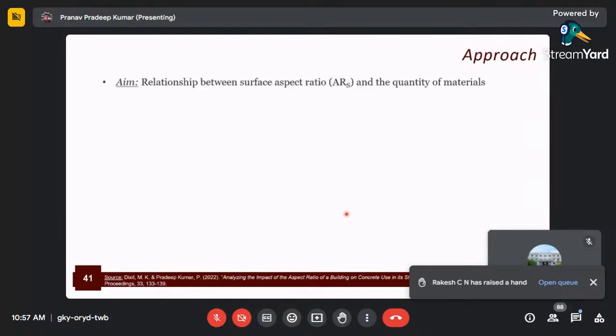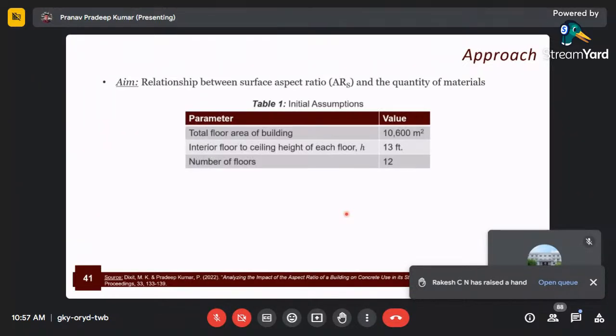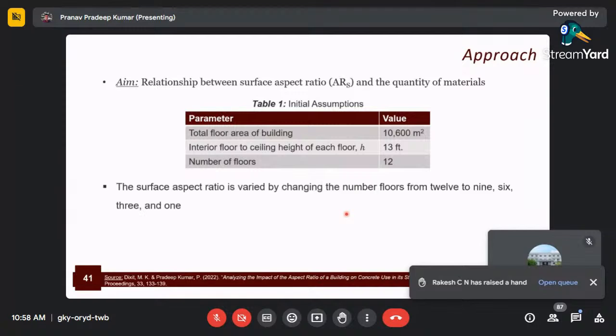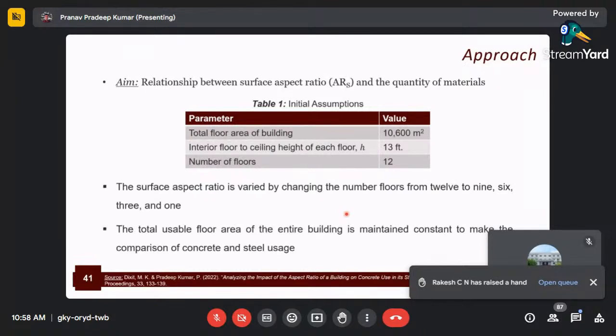So to meet our objective, we need to find a relationship between surface aspect ratio and the total quantity of materials. For this example, we began by taking an actual 12-story building with a total floor area of approximately 10,600 square meters, assuming that each floor height was about 13 foot. And then we changed the surface aspect ratio by changing the number of floors from 12 to 9, 6, 3, and 1. In order to compare the quantity of concrete and steel, we kept the total floor area, or the usable floor area within the building, a constant parameter.